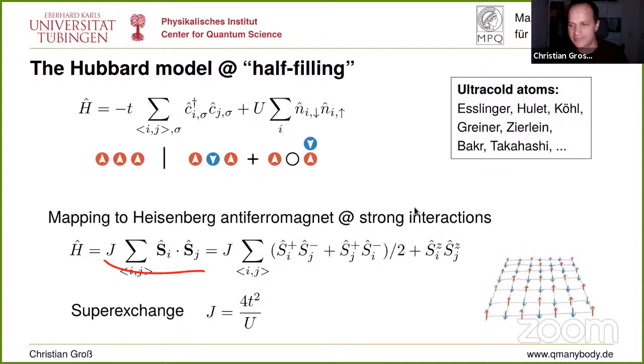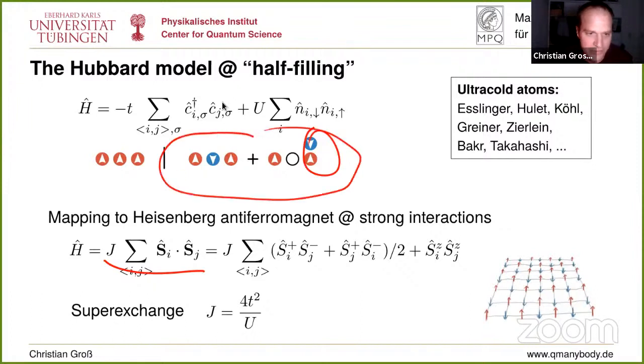And it's an antiferromagnet. Why it's an antiferromagnet is very easy to understand with my little comic here. Assume you had a ferromagnetic ground state, a block of 3 equal spins. The middle spin has no chance to even slightly delocalize to the sides because that is Pauli blocked. But if you look at the other combination, where you have a down spin in the middle, it can balance the interaction energy it has to pay against the delocalization energy it wins, which is allowed because it is not Pauli forbidden to go there. This gives you the idea that the antiferromagnetic combination is the ground state, and this is also what you get when you do the Heisenberg mapping. So this gives you some intuition why this is an antiferromagnet.